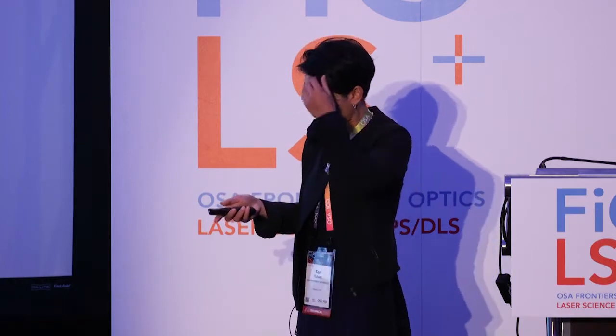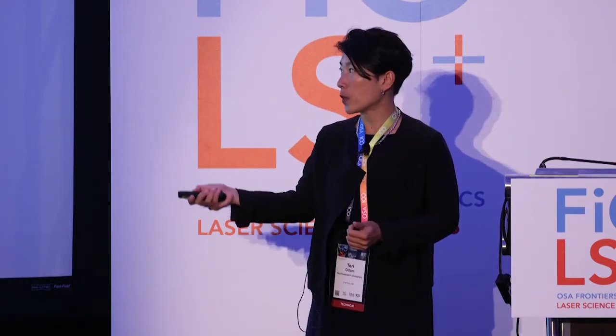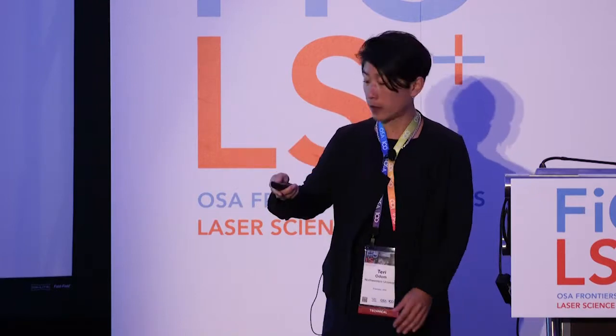but if you want to do something in the far field, that's really difficult. So in 2008, there was a proposal that said, why don't we take these little resonators, put them on a slab, and each of these little resonators can now overlap with the gain to produce some type of lasing response. This was pretty nice, so it comes out on both sides. And the array structure gives you the directionality that you might expect. However, this was at terahertz frequencies, and what we'd like to do is move this to the visible, which my group did with a much simpler system. It actually took some time from this prediction, which sounds relatively straightforward, to get to a place where we can actually start to do this. In this case, these are not split ring resonators, but just these little cylindrical particles, which I introduced earlier. You're exciting the gain, it's transferring its energy to the metal particle, and then you're getting light emission out.